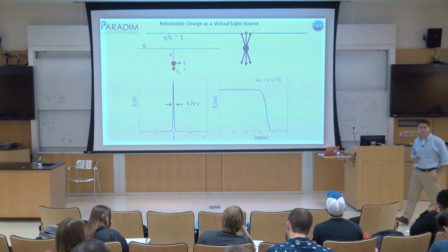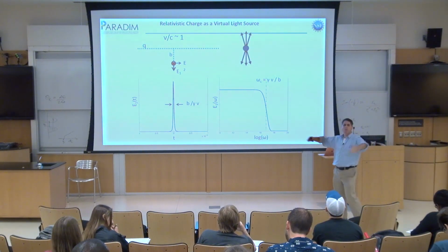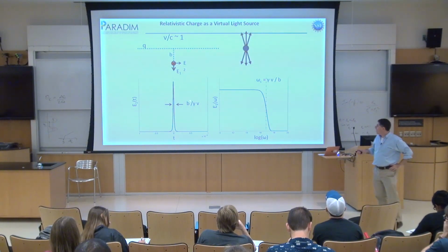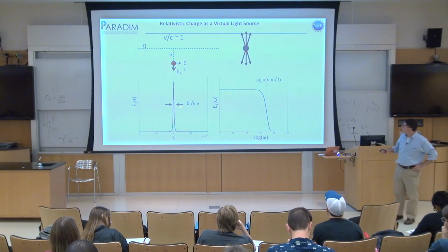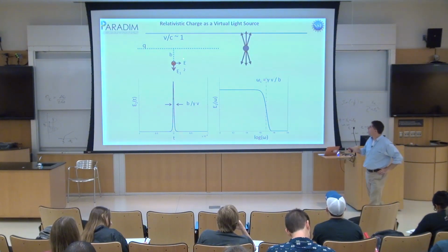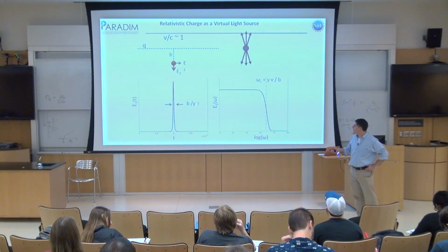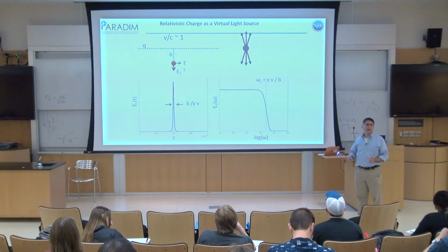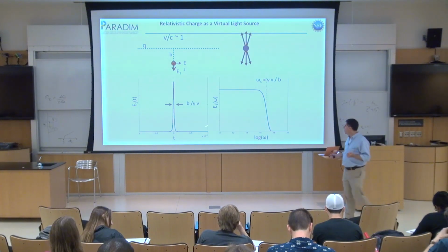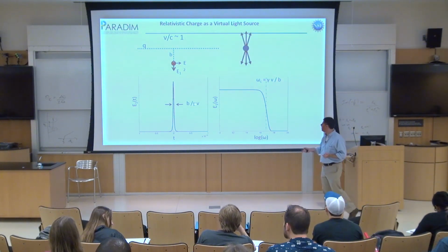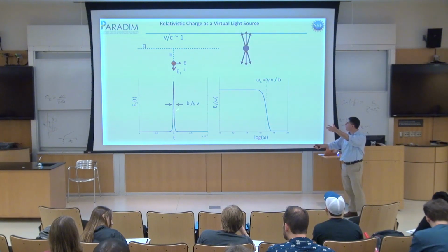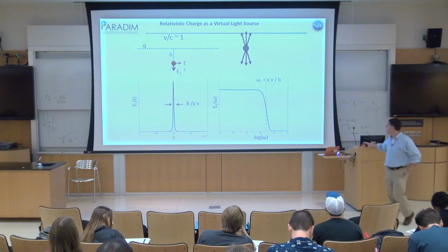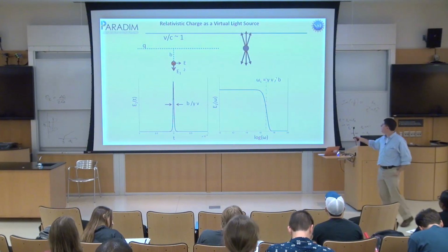So we're very, very happy. We can cover much wider energy ranges than you can in a synchrotron. The time delay for that pulse is in fact set by the velocity of the electron and the impact parameter, the distance of how far your electron is from the atom. So this little b over v is going to give me my delta t. When I Fourier transform, 1 over delta t is my delta omega. So my frequency cutoff is this thing,